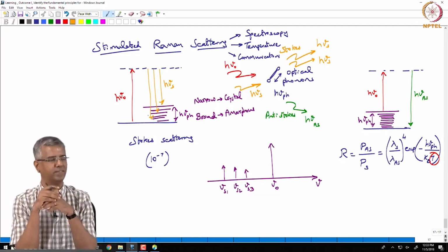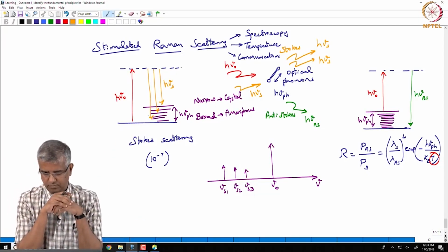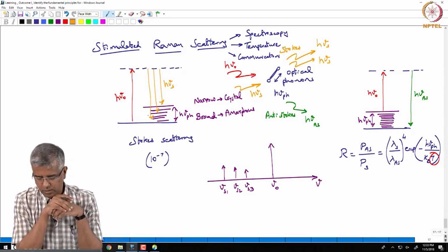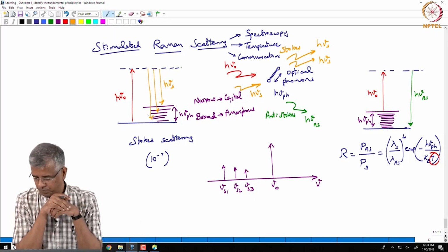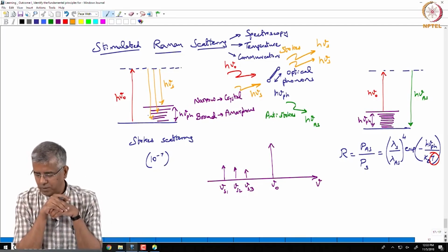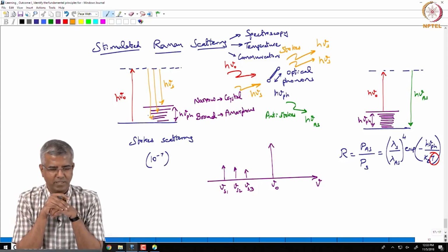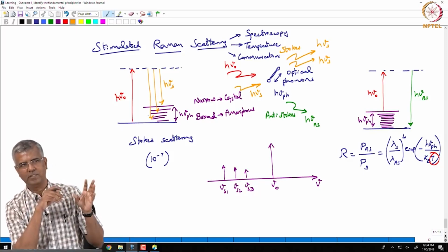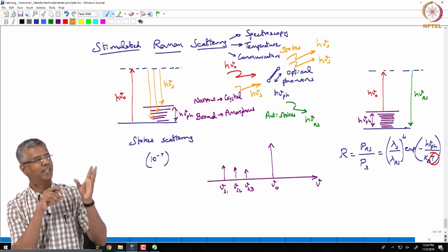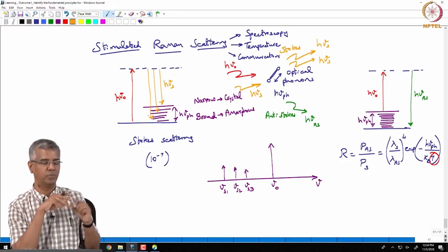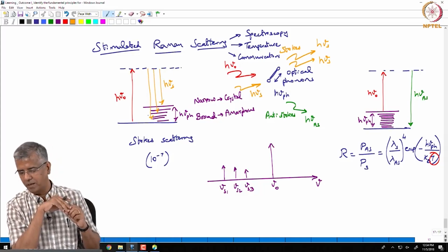So, you have a question there? Sir, what is the wave number? So, the question is what is the wave number for these phonon energies essentially. I can't remember the exact wave number, it is 1000 inverse centimeters, something like that. I don't, 500 inverse centimeter. I think it's about 500 inverse centimeter in fused silica. The phonon energy in fused silica, which is an amorphous medium, around 500 inverse centimeter is I think the peak.